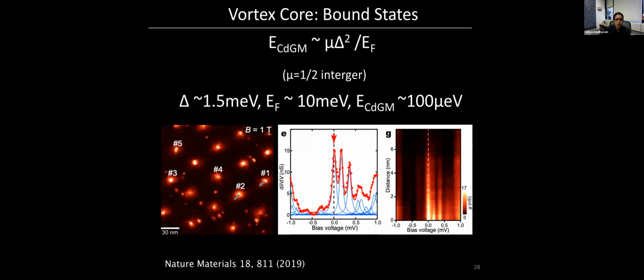So this is work done by Hanaguri's group. This is really beautiful, detailed work. And he shows many things quite clearly. One of the things he could do, because he could go to really low temperatures, is show that there are 0 bias bound states which are well within the energy resolution, good enough to say that these are well within this 100 microvolts. In fact, they're probably exactly centered at the Fermi energy. So that's pretty good proof that these are Majorana bound states.